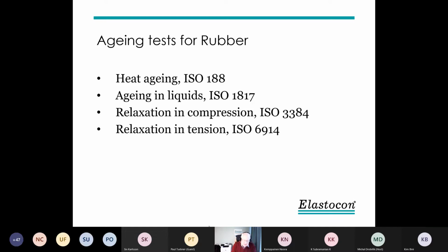The test in compression is mainly the one used because most of the materials and products you are testing are related in some way to sealing function. And then it's quite natural to do it in compression, where also two of the sides are protected and only a smaller volume of the sample are, say, in air. In tension instead, there you have a strip, which in fact should be only 1 millimeter thick, with the idea to have full exposure for the oxygen in the atmosphere. And that standard is also called that it's a pure aging test.